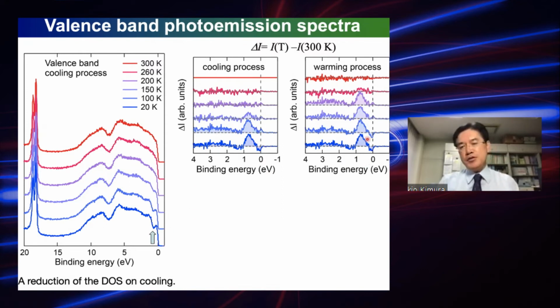In the warming process, you again see a similar change, but as you can realize, at 200 Kelvin in the warming process, you still see the dip at 0.75 eV, while this dip, this positive peak, is absent at the same temperature in the cooling process. This reminds us of some hysteresis behavior of this change in the density of states.